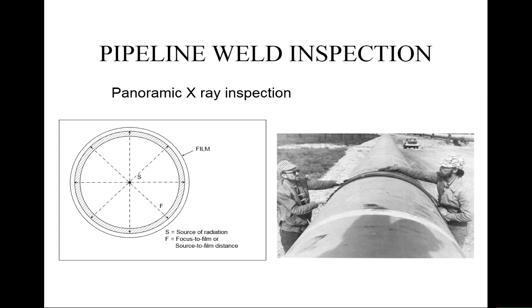So here's a very simple case, what we call panoramic X-ray inspection. The source is right in the middle of the pipe, and the crawler's designed to make sure that that source is effectively right in the middle of the pipe. And then you find where the weld is on the outside of the pipe, and you place a strip around there which has the film. So you get full 360-degree inspection of the weld from the source coming outwards. And that's very simple, but you've got to be able to have a nice crawler inside, so it tends to work better for bigger pipes.